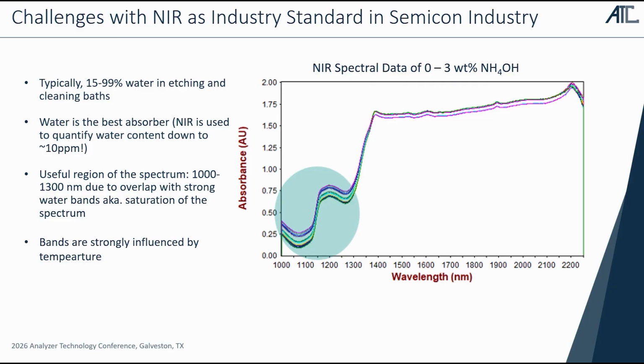And so as I mentioned earlier, industry for semiconductor and for a lot of other industries have already moved towards using spectroscopy, but there is a challenge with NIR spectroscopy, for example. For samples where you have a lot of water content in it, usually the spectrum is pretty much saturated and people still use this spectrum and do some kind of an indirect correlation to the reference values, even though there's not truly the information in the spectrum. It's saturated, it's overlapping bands, and you don't really see it anymore.